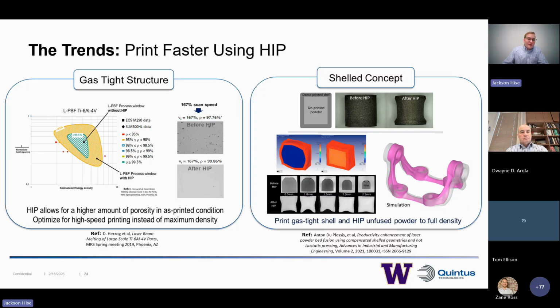So this would allow for a print faster using HIP technique where you have a lower energy density or higher hatch spacing, in order to get the same part at the end. Because even if you have defects due to this higher printing rate, you still HIP and resolve them. An extreme example of this is the shelled concept, where the structure was printed on 3 sides, fully dense, but then unprinted powder was left contained. Hipping, of course, shrunk the part, but it did create a fully dense structure of material.